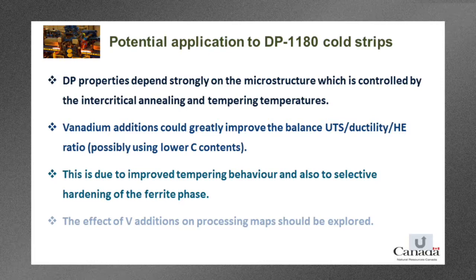Dual-phase steel properties depend very strongly on the microstructure, and that's controlled by the intercritical annealing and by the tempering temperatures that you employ. Vanadium additions could greatly improve the balance that we obtain between the ultimate tensile strength, the ductility, and the hole expansion ratio, for the reasons that I showed you in the two previous slides. That would be excellent from two possible points of view.